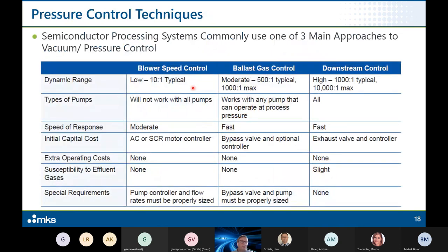In semiconductor, there are three main approaches to control the pressure in vacuum. One would be to control the blower speed or the pump speed. It only has a very low dynamic range, and not all pumps support this kind of control. The speed of response, because pumps are very often very large systems, is moderate, so speed cannot be changed very fast. Initial capital cost: maybe you need an extra controller for doing this. During operation, no extra cost, and your pump should be able to take care of the process gases anyway, so there's no extra requirement regarding the process gases. But you have to size everything very correctly to get the control range you need.